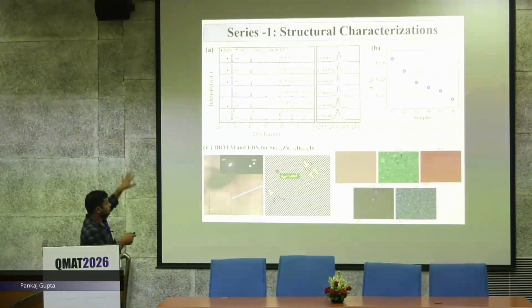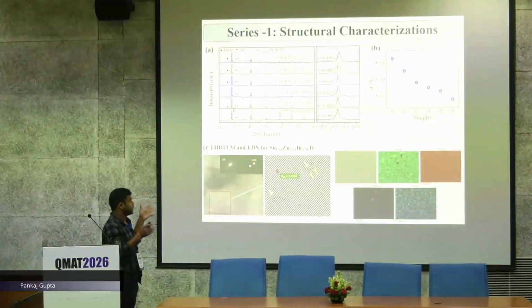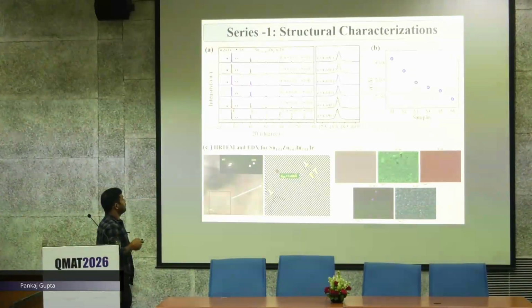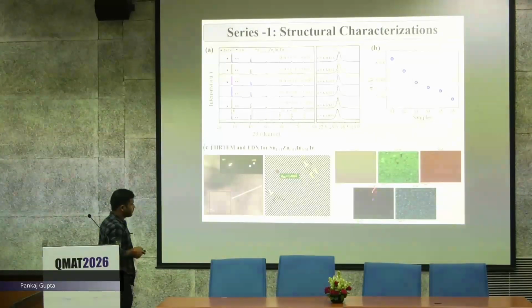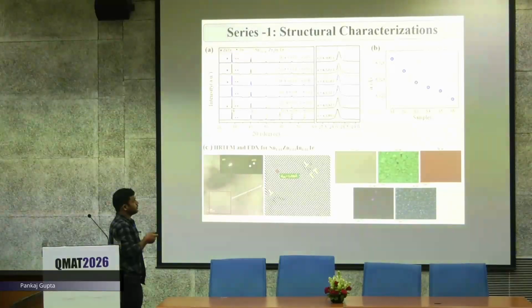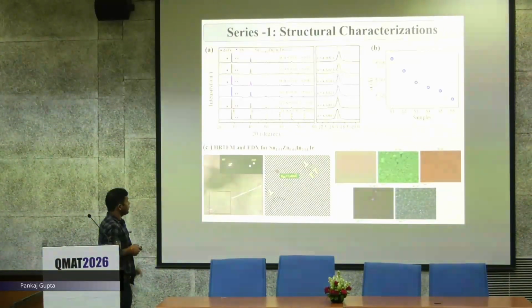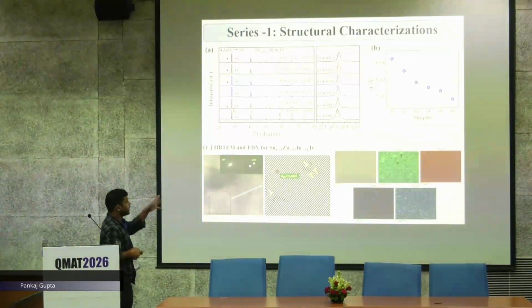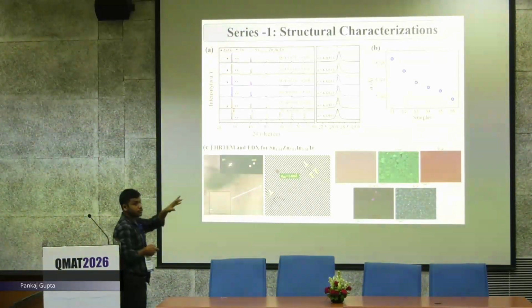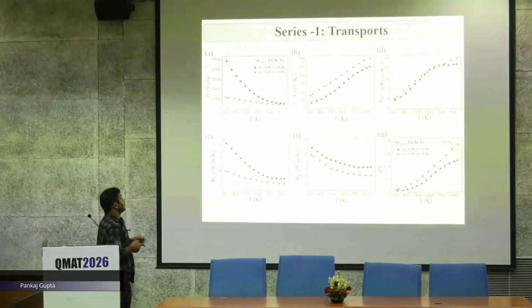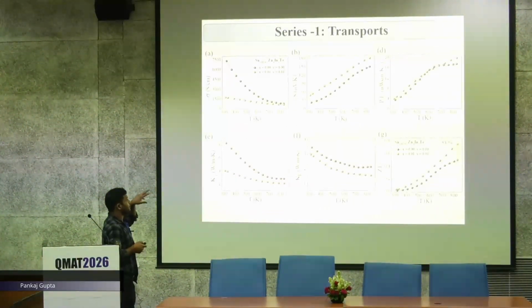And then I looked at the XRD, a picture of the phase purity of the sample, and we found that all the samples are nearly pure except some Sn and zinc impurity, as you can see in the FESEM imaging. All the doping is following Vegard's law because of the lower size of zinc and indium. With this alloying, we can see there is some lattice disorder in the system that is very helpful in reducing the lattice thermal conductivity. So out of these 5 samples, in the interest of time, I have put only 2 samples: the pristine and the best sample which I found.